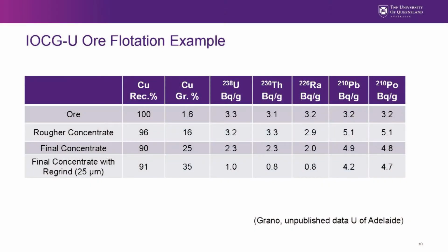So here's a table of IOCG ore in an example in the first row. And then what happens when you grind it up and send it through a rougher concentrate, you can recover 96% of the copper and get upgraded 10 times from 1.6 to 16% copper. And the radionuclide distribution doesn't change too much, but if you notice the lead and polonium 210 actually preferentially deported to the copper mineral phases that were floated.